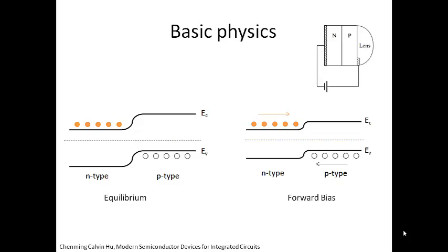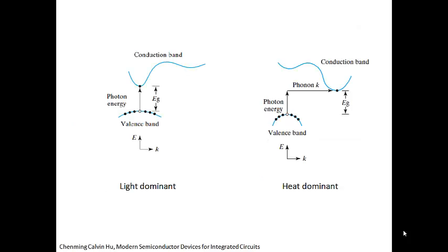For direct semiconductors like gallium arsenide, the crystal momentum of the electrons and holes are about the same, and a significant portion of the injected carriers is eliminated by band-to-band recombination. Therefore, the energy is mainly released in the form of photons and becomes the light produced by the LED. For indirect semiconductors, recombination takes place predominantly through RG centers, so that a huge amount of the energy released during the recombination process is in the form of heat.